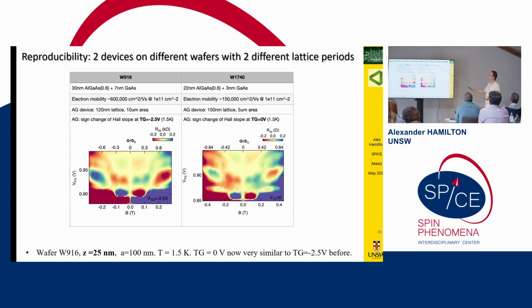This is a completely separate wafer. It's a different depth, a different electron mobility. The lattice constant is different. And yet these pictures look really, really similar. And if you take this data and normalize it for the change in lattice constant, you can just move it straight over and plop it on top of the other data set. So these are 2 completely different lattices, completely different wafers. In mesoscopic physics, I never see anything like this happen.